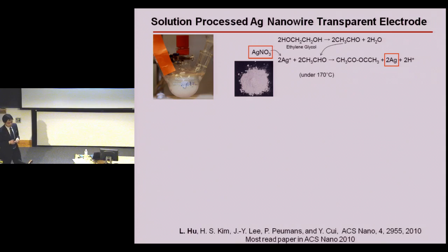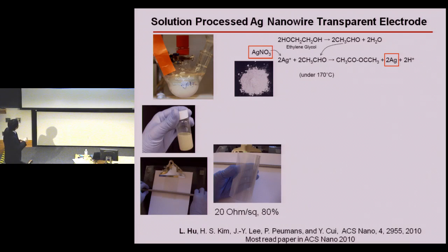So based on this calculation, I started to make silver nanowire solutions using this simple chemical reaction. Basically, ethylene glycol will reduce silver from silver nitrate at a temperature of 170 degrees. After some purification and centrifuge, we get a very nice silver nanowire ink. Based on this ink, we can print a transparent electrode on plastic or glass substrate. So here is the transparent and conductive silver nanowire film on top of a plastic substrate with performance of 20 ohm per square and 80% transparency.